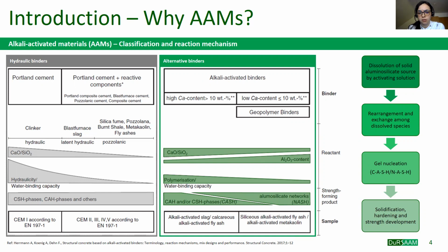groups can be defined. High calcium silicon-rich binders, which react with alkaline solution, leading to the formation of a C-A-S-H gel, and the low calcium alumino-rich binders, such as fly ash or metakaolin, which, reacting with an alkaline solution, lead to the formation of a N-A-S-H gel. In this work, only the first group of binder is investigated.